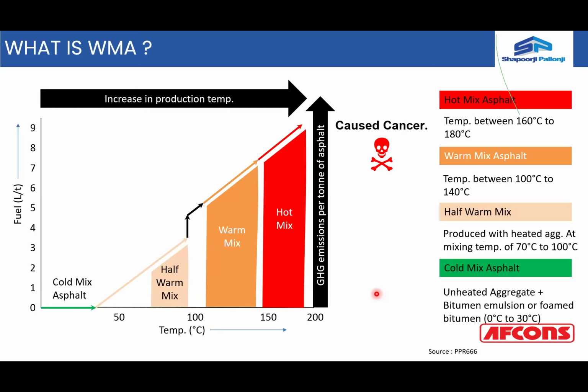Again, the mix temperature depends upon the type of asphalt being used, because we are using, say, 20/30 binder, which is normally not used here in India. But if you look at the French specifications, they have 20/30 grade binders also, wherein the mix temperature is close to 190 degrees. It's neither 150 nor 100, but close to 190 degrees if you are using only 20/30 grade binder. In case of VG40, you have a mix temperature close to 155 to 160.